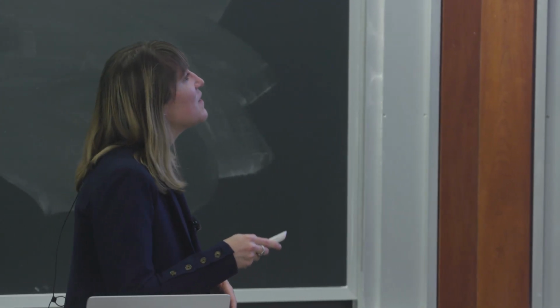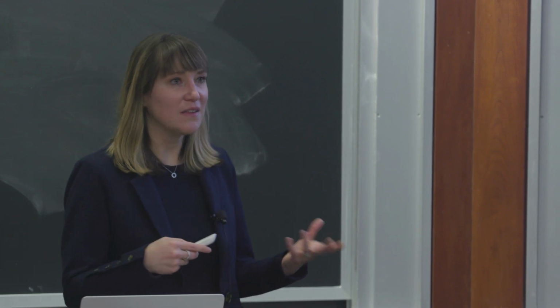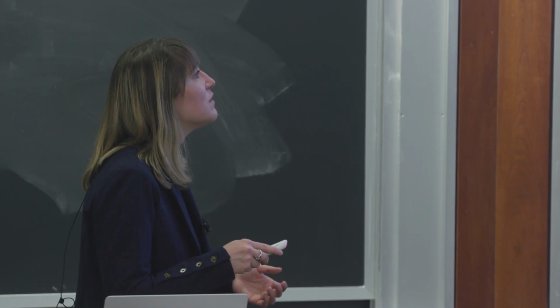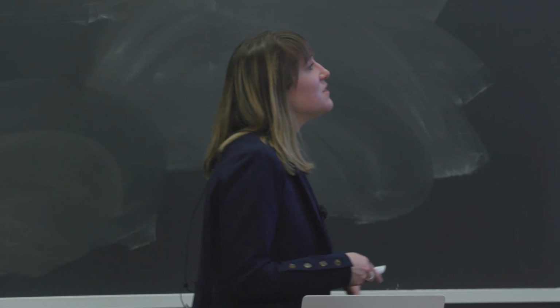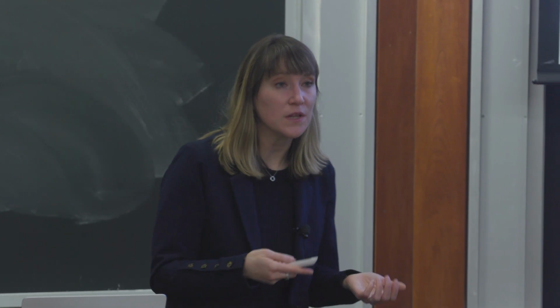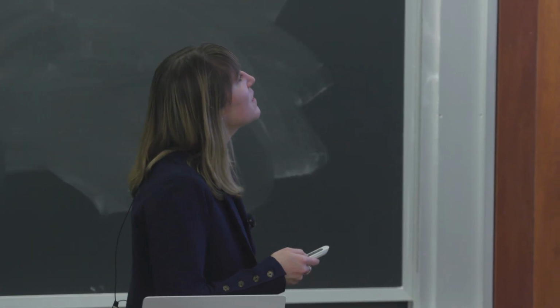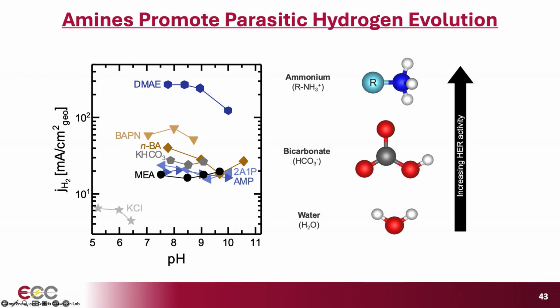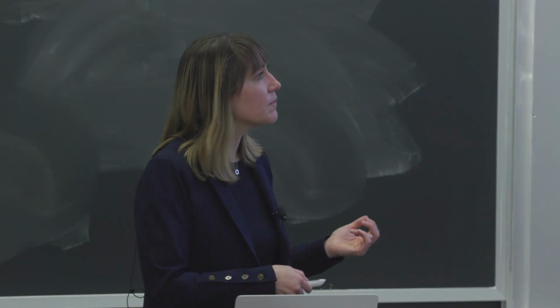But this CO2 actually has interesting pathways to regenerate it as it's consumed at the electrode surface, for example, through dehydration of bicarbonate. So that helps us gain a picture into kind of how we might further design these systems. We really want to maximize the dehydration or the regeneration of CO2 locally at the electrode surface. But another thing that we observed in these systems is that the systems with amines present tended to have elevated hydrogen evolution rates. And I mentioned before, we have multiple potential hydrogen evolution reaction participants. We have water, bicarbonate, and ammonium. And disentangling all of these different contributors is challenging in a system where they're all kind of mixed together.